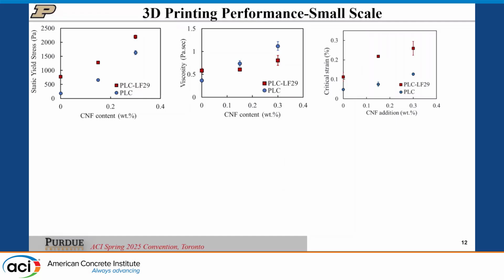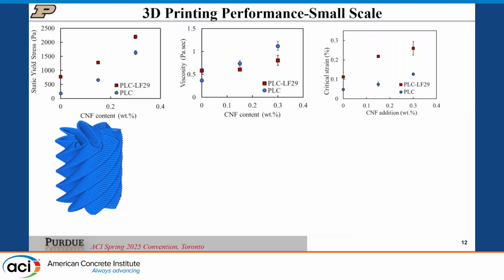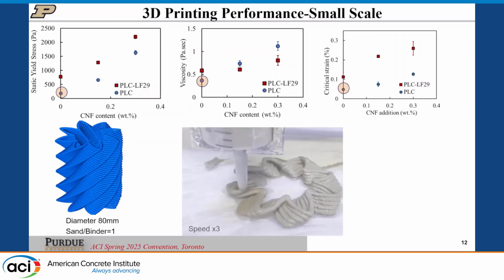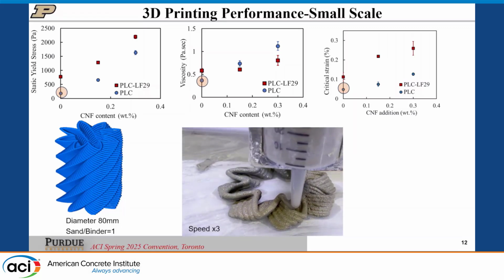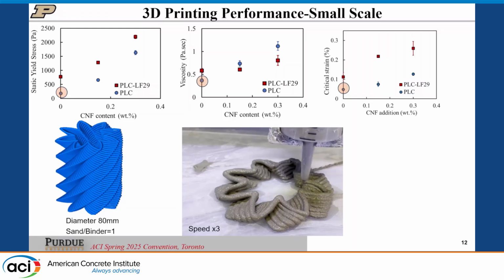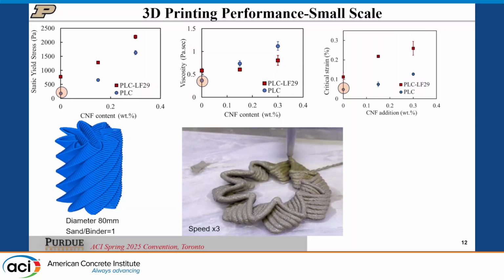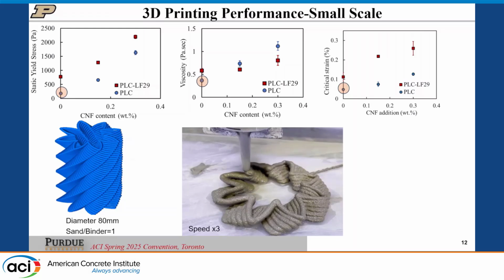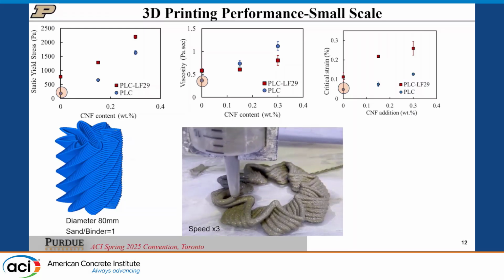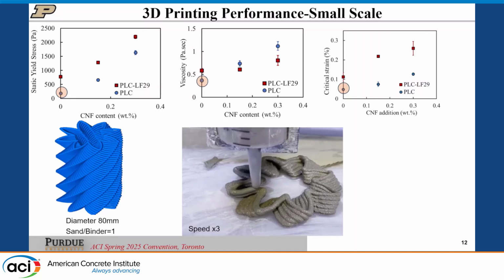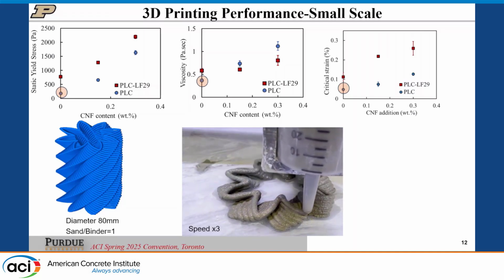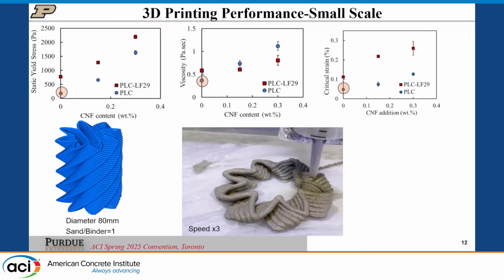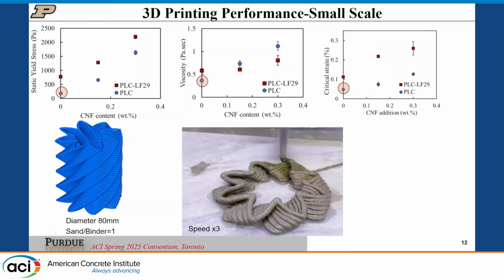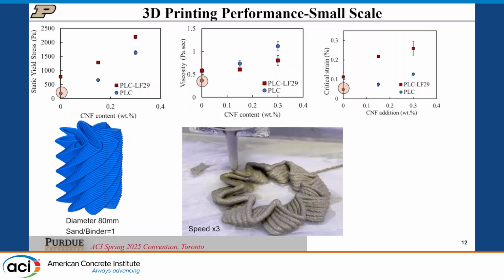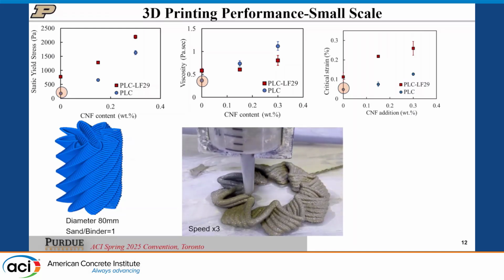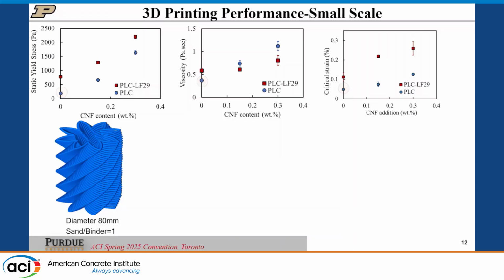If we take all the rheological properties and translate them into printing, we can see how the printing system acts - first on the small scale with mortars containing very fine sand particles. For the first mix, with nothing added, very early on the print starts failing. We're trying to challenge the print using a rotating structure so we can also look at effects on elastic modulus and buckling. Very early on, you see this print is not going very well.